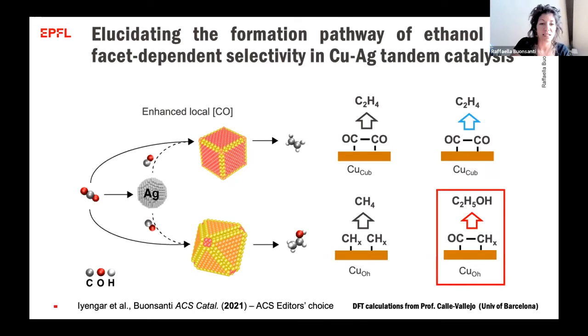I mentioned that silver and gold are highly selective for CO, so silver produces CO, and it creates basically an enhanced local concentration of CO around the copper cubes and the copper octahedra. What we found here is that the copper octahedra were actually becoming, in the presence of enhanced local concentration of CO, highly selective for ethanol compared to the copper cubes that instead remain selective for ethylene.